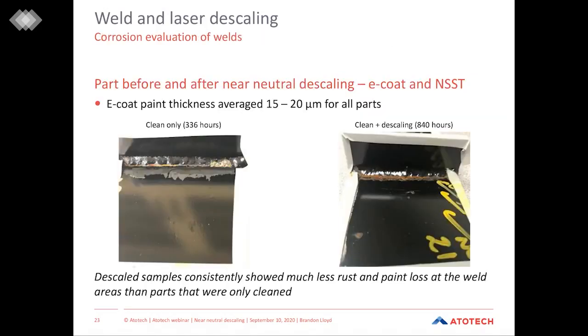Yes. Okay. Was a tape pull test used after corrosion testing on the parts shown in slide 23? Yes, that is correct. So it was a tape test along the weld that was used to evaluate these parts. And so you can see from the clean only application on the left after 336 hours that there's quite a bit of paint that is removed from the tape test. And we see that the part that was cleaned and then descaled with UniPrep AC after 840 hours of neutral salt spray exposure, we see very minimal loss of paint from the tape test. So yeah, to answer that question, that is how we evaluated, was with a tape test.